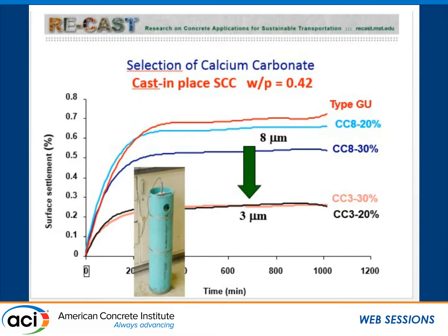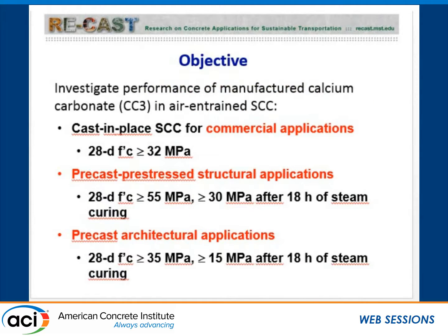The study was continued using the calcium carbonate with the 3 micron D50, and we had 3 classes of SCC that were all air-entrained. The first one was for commercial applications. So the targeted compressive strength at 28 days was 32 MPa. The second one was the precast, pre-stressed structural applications, so for girders and beams, pre-stressed elements. And there the compressive strength at 28 days was 55 MPa, and the 18-hour compressive strength after steam curing was 30 MPa. And the last application we were interested in